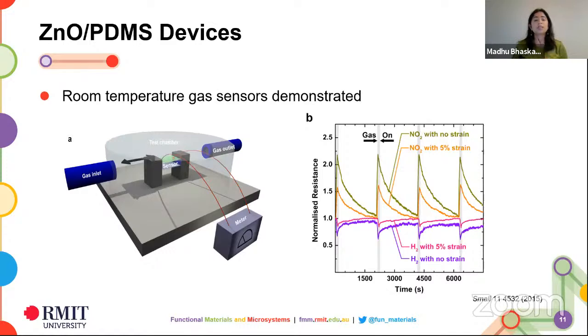Now, using this, we demonstrated a couple of applications. So we tried demonstrating gas sensors using zinc oxide. Now, typically, if you work with gas sensors, you would know gas sensors don't really work at room temperature. You need to actually heat them up to around, say, 150 or 200 degrees centigrade to get them working. The amazing fact was these were gas sensors which actually work at room temperature. So even at room temperature, you're able to sense and pick up the difference in the gases.